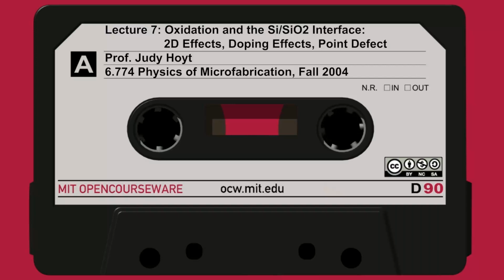On the lower right, which is kind of interesting, this is from the HP process, this is the actual experimental data. So they made this SWAMI process, and then they did a polished cross-section scanning electron micrograph. And this is the active silicon region afterwards. This region right here is the oxide and the nitride. And you can see, if you compare the simulation upper right to the lower right, the actual data, it's not that far off. It reproduces some of the key features. You can see this little divot here, this little V-shaped well. Well, that's also what you've seen in the simulation.